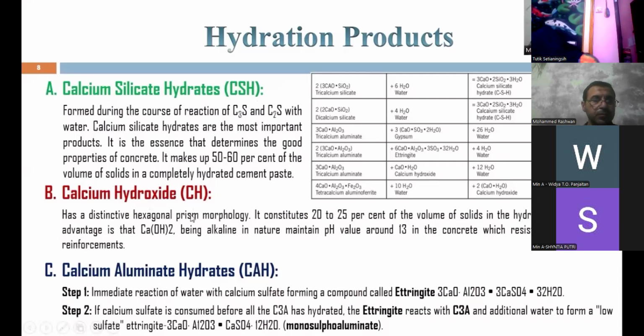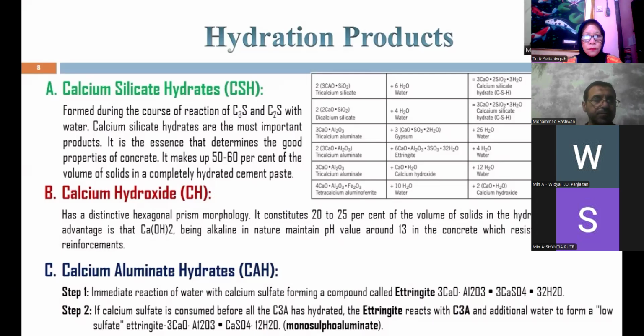And calcium hydroxide has a main advantage, especially for reinforced concrete. How can this phase be helpful for reinforced concrete? The alkaline nature of this phase, with a pH maybe around 13, helps protect the concrete, especially reinforced concrete, from being corroded by sulfate attack or any other attack medium.